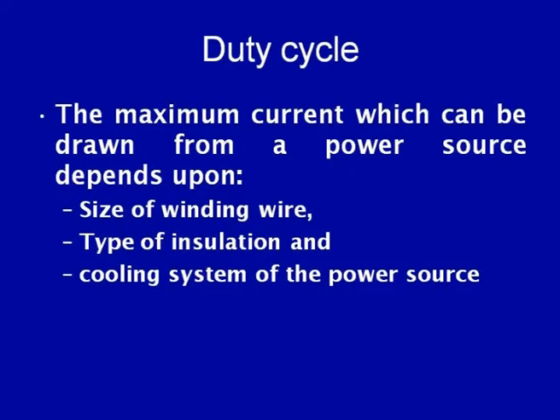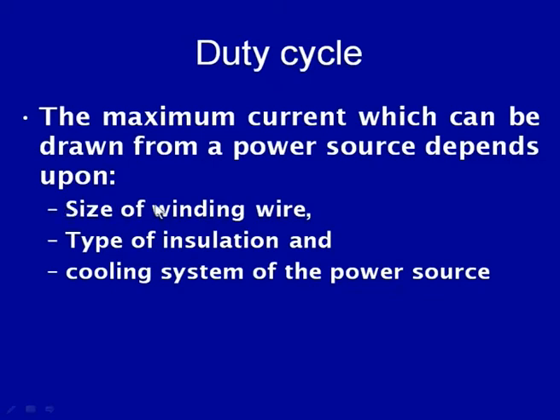So, the factors that affect the duty cycle and their capability to draw the high current: the maximum current which can be drawn from the power source at a particular duty cycle depends upon the size of the wire. We know that the electrical resistance heating is governed by the electrical resistance being offered by the conducting wires being used in the cables and the coils. If the size of the wires is big, then electrical resistance for the flow of current will be low, which in turn will lead to less electrical resistance heating, and the reduced heating will allow a higher duty cycle, or it will have the greater capability to draw more current for a longer duration.